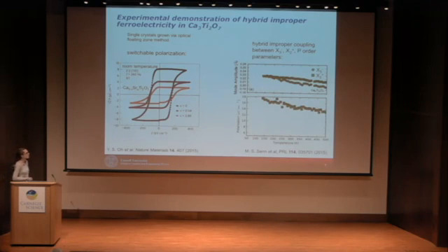So over here are some XRD results showing the temperature evolution of the amplitude of the two octahedral rotation modes in the top and the polarization in the bottom. And these all evolve with temperature proportional to one another, as one would expect in a trilinear coupling mechanism. In addition, the temperature dependence of the polarization is linear in temperature, so it's improper-like, which is significant. There are other trilinearly coupled ferroelectrics, such as the Aurivillius phases, that are more proper-like.